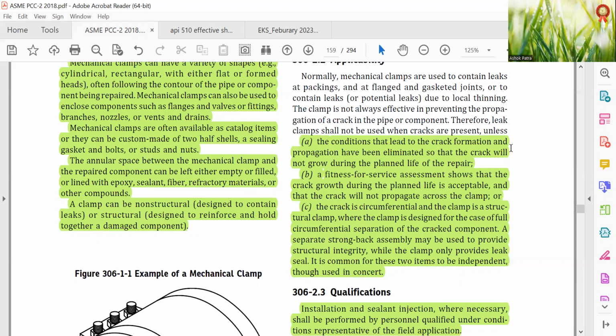The conditions that lead to crack formation and propagation have been eliminated so the crack will not grow during the planned life of the repair. A fitness-for-service assessment shows that the crack growth during the planned life is acceptable and the crack will not propagate across the clamp, or the crack is circumferential and the clamp is a structural clamp, where the clamp is designed for the case of full circumferential separation of the cracked component. A separate strongback assembly may be used to provide structural integrity, where the clamp only provides the seal. It is common for those two items to be independent though used in concert.